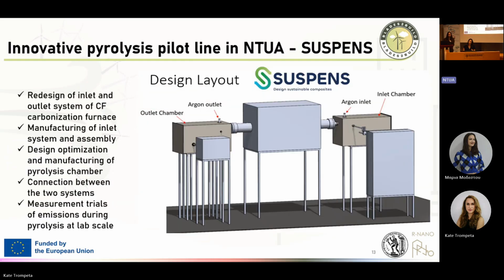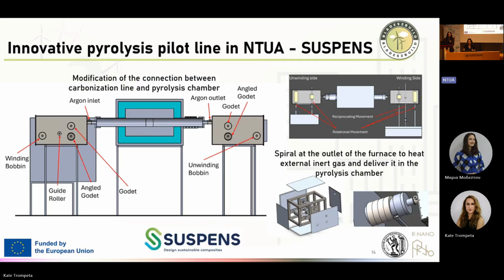So this was the design of the pilot line that we have here in NTUA. We already had a carbonization furnace working as a batch process. So we have redesigned the inlet and outlet system. We have actually manufactured a connection between the two systems, which is the carbonization furnace and the pyrolysis. And we have also tried to optimize the energy needed for both. Here you may see some of the modifications and designs that have been carried out by our team in collaboration with the Mechanical Engineering School.